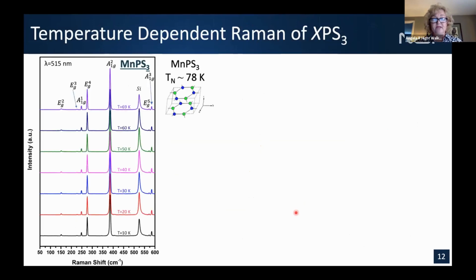So here are some examples of temperature-dependent Raman. Here we're looking at the MnPS3 with the Néel temperature of near 78 degrees. Now, all of these spectra are below the Néel temperature, but you'll note we're not seeing a lot of change by eye. Of note, right now we're using excitation at 515 nanometers, a green laser. You'll see throughout the talk, we'll be switching different lasers. Again, that's one of the assets of our capability.